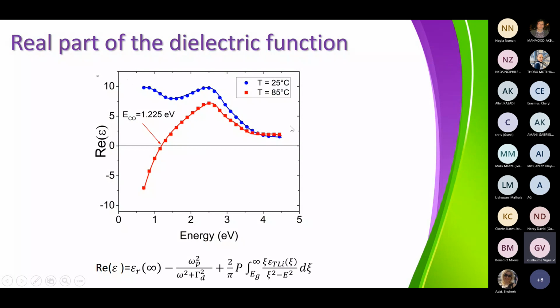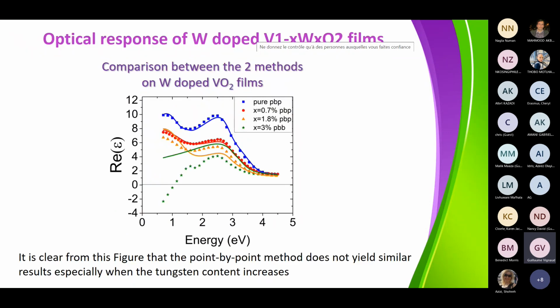So it's really typical of what you will see if you have a conductive material, a metallic material. If you are in an insulating phase, you can see that the real part is always positive. So fine, we understand what's going on in the pure. Now we want to see what's going to happen if we dope the material. And if we dope the material, that's what we get.